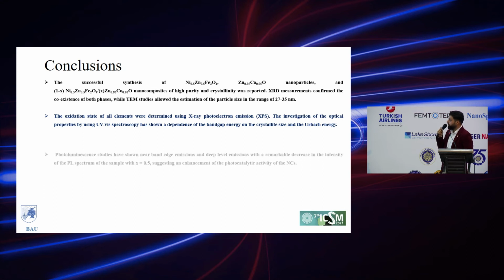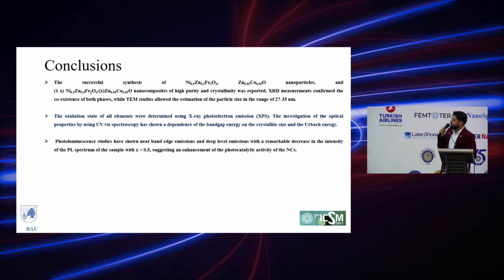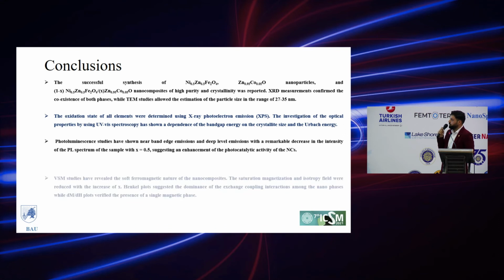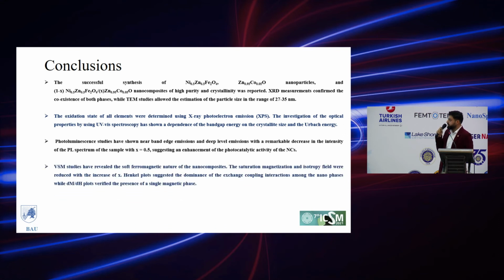Photoluminescence studies have shown near-band edge emissions and deep-level emissions, with a remarkable decrease in the intensity of the PL spectrum for the sample with X equal to 0.5, suggesting an enhancement of the photocatalytic activity of the nanocomposites. VSM studies have revealed the soft ferromagnetic nature of the nanocomposites. The saturation magnetization and anisotropy field were reduced with the increase of X.